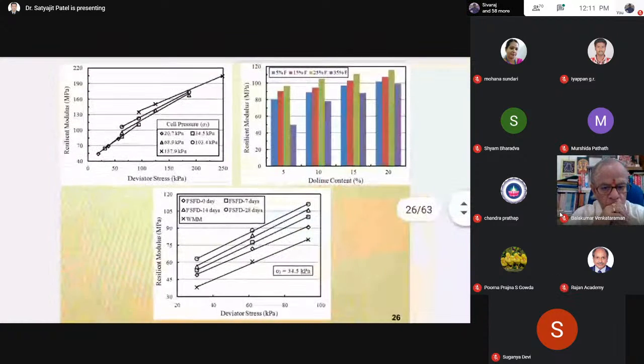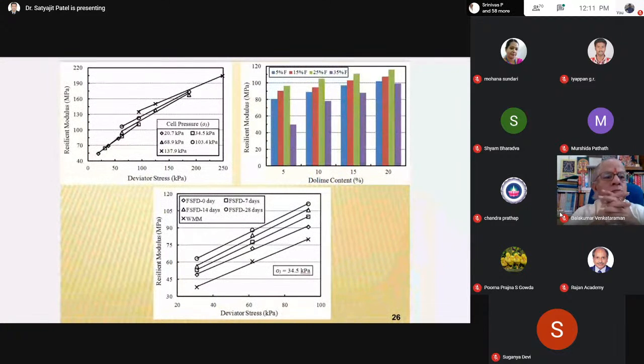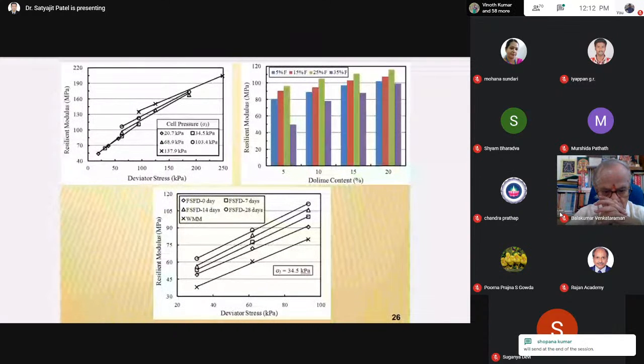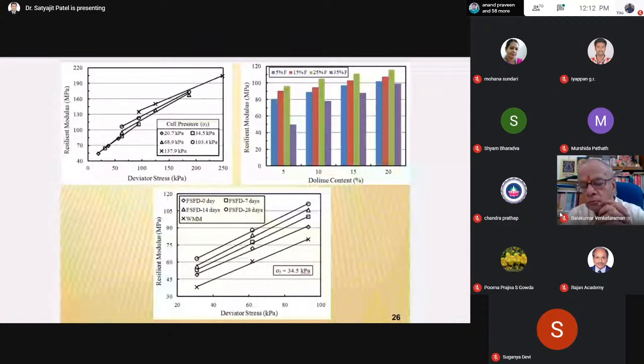This has been obtained for the fine steel slag flash dolomite mixes. Similarly, the resilient modulus can be plotted with deviator stress. Then the resilient modulus has been plotted with dolomite content. At higher dolomite content, you will get a higher resilient modulus. The higher the binder content, the higher its compressive strength, and the higher its stiffness value. Similarly, resilient modulus with deviator stress has been plotted here for different curing periods.